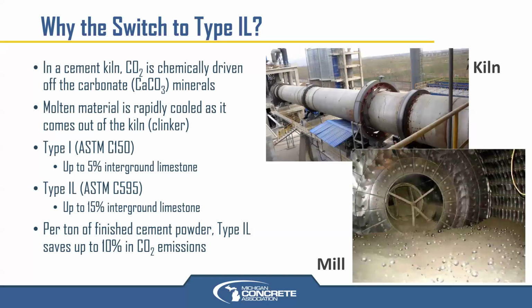So the old Type 1 cement that people were familiar with fell under a specification called ASTM C 150, which limited the amount of limestone added to the mill to 5%. So we're talking about raw limestone that did not go through the kiln, that's then added to the mill with the clinker and with gypsum, calcium sulfate, for those chemistry nerds like myself that want to know. The gypsum is used to help control the set. They do a certain amount of that. The limestone is essentially an inert powder. It does have some benefits to the cement hydration process, but it was limited to 5% under old specifications.